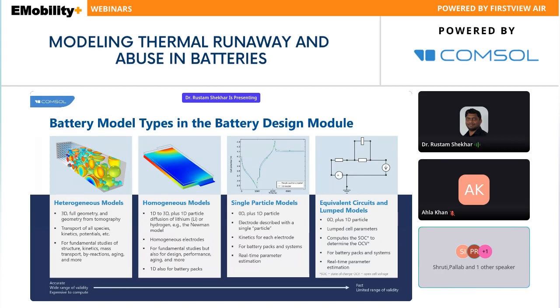Here you can include the thermal effect, structural effect. If any kind of flow like gas generation is there and you have a two-phase flow, then you can add that as well. So how is it helping in the thermal runaway scenario? Let's say you are having lithium plating on these particles. Then you have an electrochemical reaction happening on the surface, and if there is a difference between the mass transport in the bulk, which is the electrolyte, and mass transport in the solid, which is intercalation, then you will start accumulating lithium on the surface, and that will grow as a dendrite, and it may puncture your membrane. That scenario may occur at high C rate conditions and low temperature conditions.